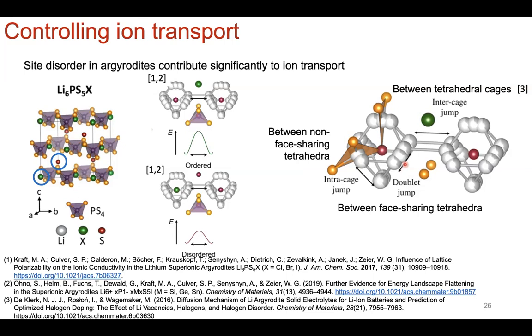Now, in terms of the X position, it can be a halide. So it could be chloride, bromide, or iodide. With the bromide and the chloride species, you have quite a bit more site disorder. So where the sulfide ions sit versus where the halide ions sit, they sometimes will just switch during synthesis. And that's just thermodynamic equilibrium. You put the precursors in, you shake or stir or what have you. In terms of site occupancy for where sulfides can go and where the halides can go, there's quite a bit of mixing that occurs for the chloride and the bromide. The iodide is quite large, and so it's anchored to those 4a, 4c sites. It's quite ordered, which is not a good thing because that means your activation energy is much higher than for a disordered system. So the chloride and bromide systems introduce a lot of site disorder, which will increase ion conductivity.